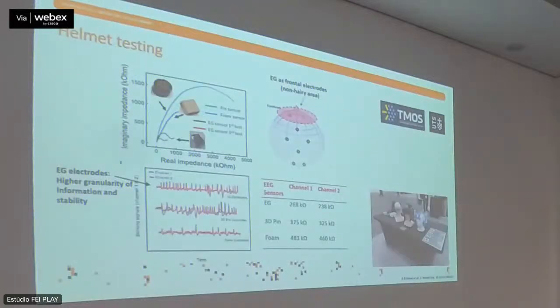And I just wanted to show you very quickly the difference that it makes. So I talked about contact impedance, but also just imagine, this is the 10-20 system, basically the map of the skull that people use in EEG. And we're using the frontal channels with graphene. And we're swapping between our graphene sensors and the commercial sensors. And this is a signal. Now, don't worry about what that means, because that's a different story. But all that you can really see is that the level of detail picked up by the graphene sensors in this case is much more detailed, much more accurate than, for example, these other ones here, which have much less detail. So here you can see that the contact impedance really relates to the quality of the signal that you're going to pick up through the helmet.